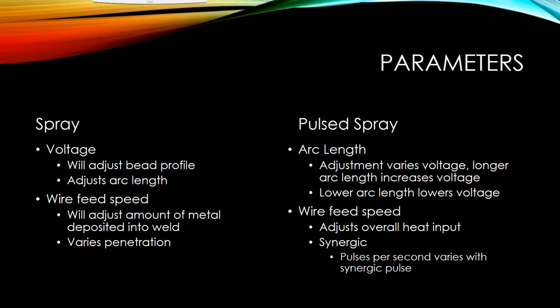Now it shifts gears when we jump over to pulse spray, because our two main adjustments are arc length, or arc adjust is another common term for it, and then we're also going to be using wire feed speed. With our arc length, we're talking specifically about the distance between the end of the wire and the molten puddle. We can adjust how big that distance is. The adjustment affects our voltage: a longer arc length will increase that voltage, and a lower arc length is going to lower the voltage. And it'll tighten up. I've got a couple of videos that we're going to look at here in a second.